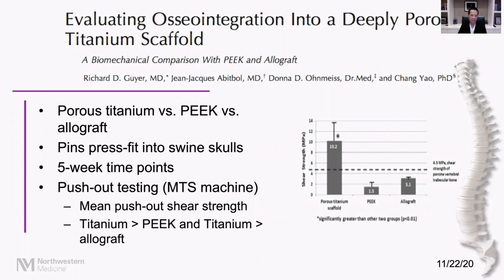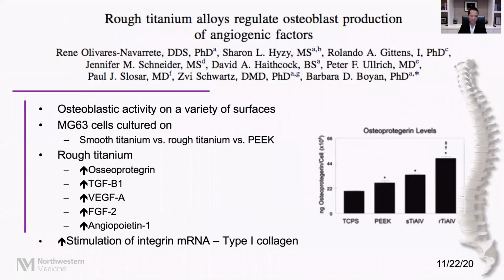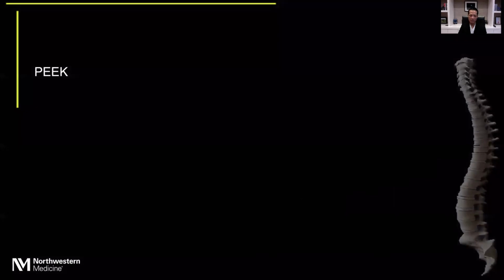As far as osseointegration is concerned, there are many studies that have compared titanium to PEEK, and these studies illustrate that it's not just the material of titanium that is important, but also the surface and the amount of porosity that we see. The more porosity that you see with PEEK, the better the integration is compared to pure material, and the same goes for titanium. And when one looks at the osteoblastic activity on a variety of surfaces, including smooth titanium, rough titanium, and PEEK, there's no question that roughened titanium performs the best in an in vitro setting.